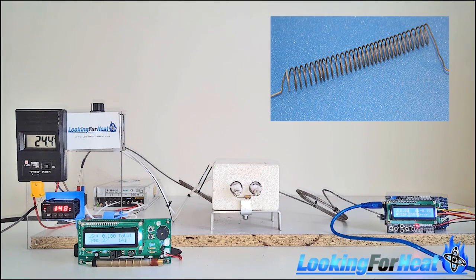The limitations are probably the superheater Kanthal wires because they start softening around 1400 degrees, and also the K-type thermocouples that we're providing with the systems. They're only intended to measure temperatures up to 1350 degrees.